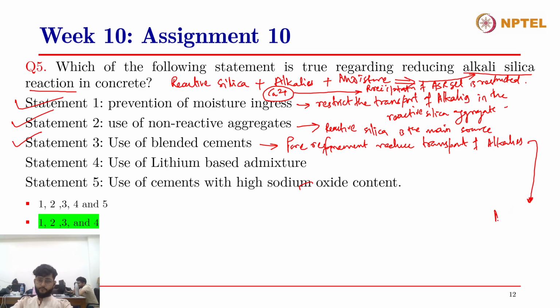So amorphous silica plus portlandite coming from the hydration of the clinker produces additional CSH in the concrete. Now, when the calcium hydroxide is consumed by these SCMs, the calcium ion concentration in the pore solution is reduced, and therefore it also reduces the risk of alkali silica reaction. So that is also one way how blended cements help reduce the risk of alkali silica reaction.